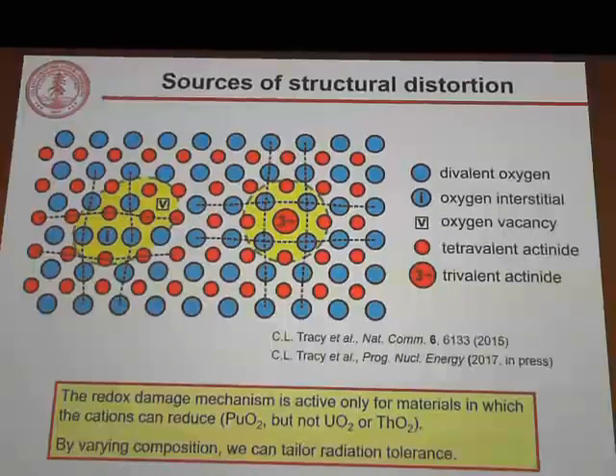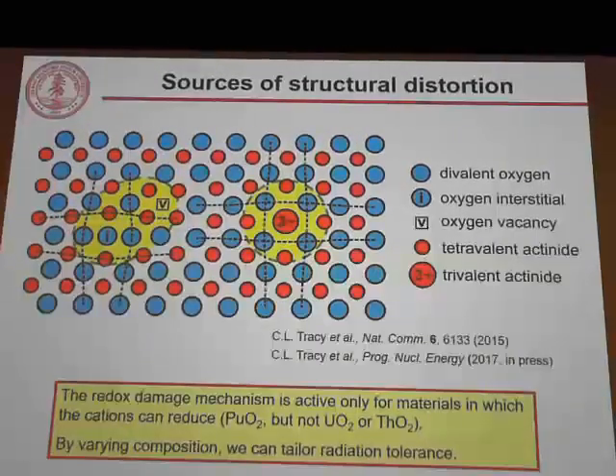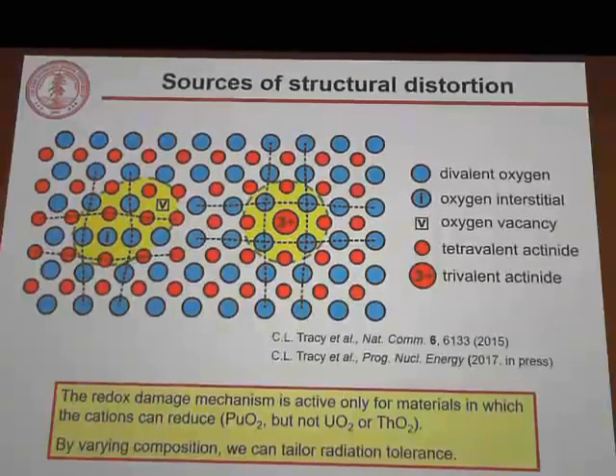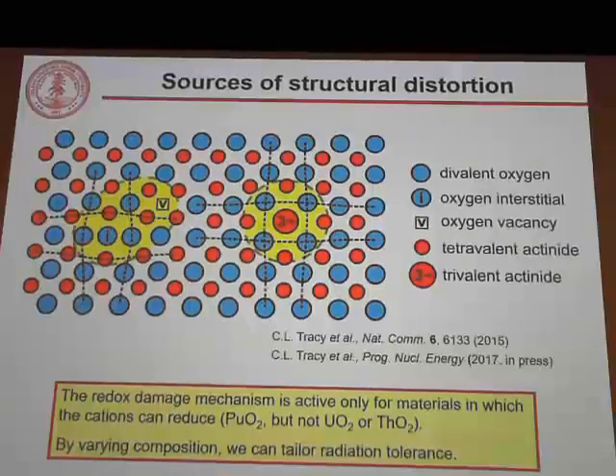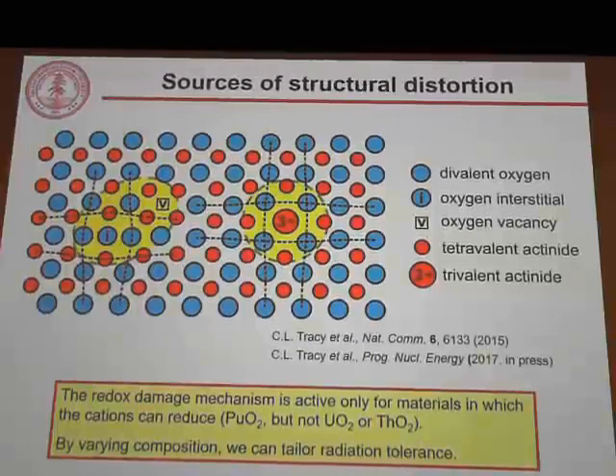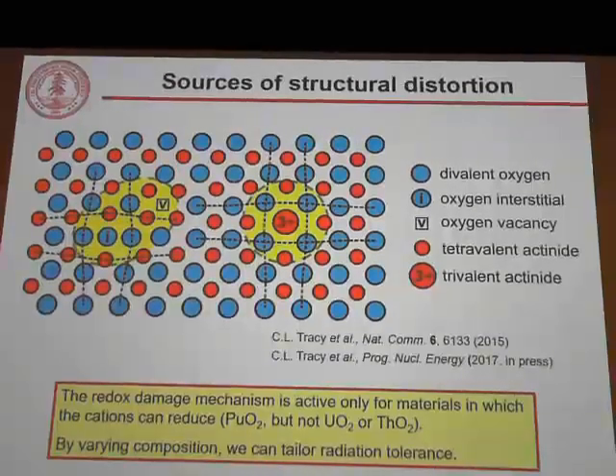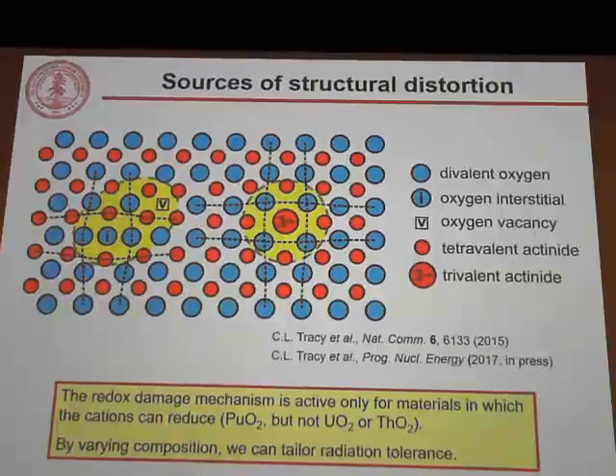So from this, what we've learned is that there is an alternative damage mechanism, but one that is active only for some materials, those in which the cations can reduce from their tetravalent state to the trivalent state. This means, for example, that plutonium dioxide will likely have a very different radiation response than uranium and thorium dioxide, as in the latter two materials, you don't have reducible cations in the form where you do. And this tells us how by varying the composition of a fuel, we can to some extent tailor its radiation tolerance once we understand the mechanisms that are resulting in this damage.